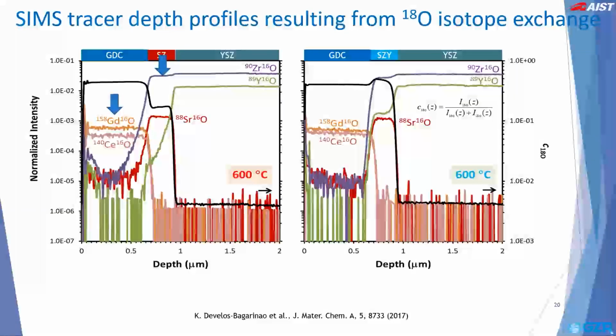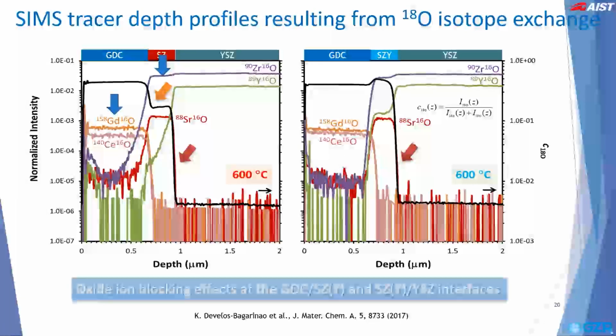What is interesting about the 18O plot is the fact that whereas they show a rather high concentration in the GDC region, indicating very fast diffusion, they exhibit sharp drops at the interfaces with strontium zirconate or yttrium-doped strontium zirconate. This indicates that the oxide ion transport is significantly blocked at such interfaces, which suggests the existence of oxide ion blocking effects. These results therefore indicate that the degradation and cell performance can be associated with the blocking of ionic flow at such interfaces.